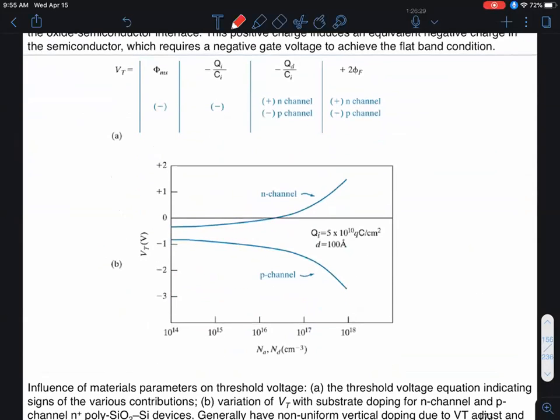So now you're able to put all these terms together to get the actual expression for the threshold voltage. Earlier, when you had the ideal diode, we assumed that the flat band voltage, which is these first two terms, was 0. So to get that, you added the voltage drop in the semiconductor to the voltage drop across the oxide, where QD equals q Na Wmax, where Wmax depended on doping in two places: log of Na over Ni in the numerator, and then Na in the denominator. But now we've added two more terms, which is the work function difference between the metal and the semiconductor, and then the effect of the charges mapped to a delta function charge at the interface over Ci. Okay.